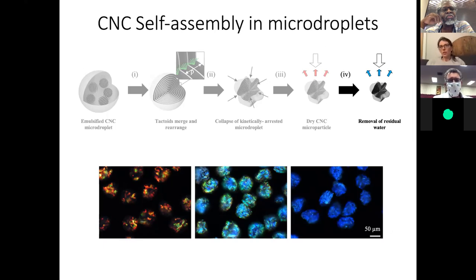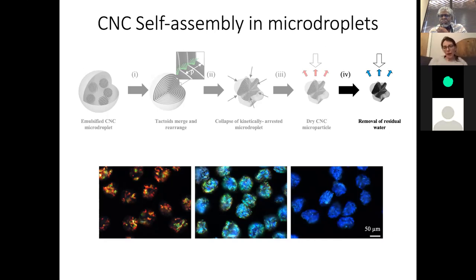So the way we do it, I would say that it is not really environmentally friendly, just because we are starting now to use other methods. Other people have published methods where they produce good cellulose nanocrystals that I think would work for what we want to do, using, for example, ionic liquids or deep eutectic solvents. There you can do recycling of these ionic liquids during the manufacturing process and obtain similar performing material. So in short, what we do, I wouldn't categorize as green chemistry. We end up having a material that is, in my opinion, more sustainable than a plastic, because at the end it's still a biopolymer, but the hydrolysis process is really not green.